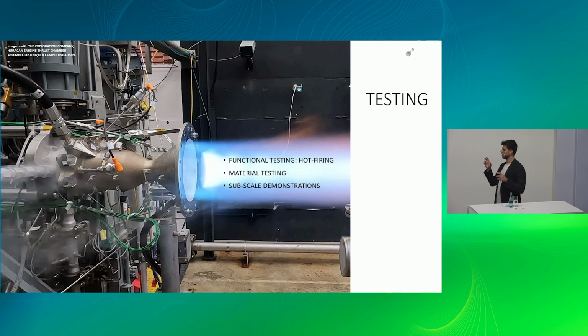You put the parts on the test bench, and then you fire the parts with a lot of thermocouples and pressure ports. You check what is the temperature and the pressure situation along the part. You then compare if that is the same as you simulated in your simulations before. If there's a difference, this delta will go into the next generation of engines, into the next iteration. And that's basically also the concept how you develop rocket engines. You design, you simulate, you build, you put it on the test bench, and by these values and these measurements that you get, you try to make the next generation of the engine better, and then put it on a test bench again. So that test bench is the qualifying part in the end.